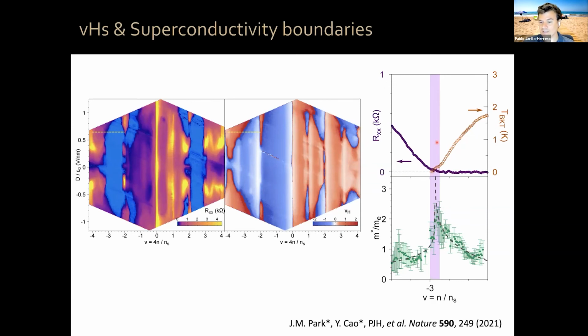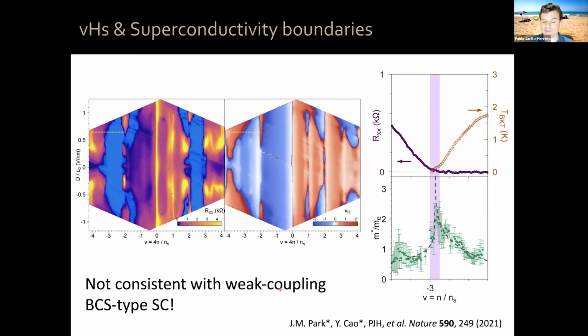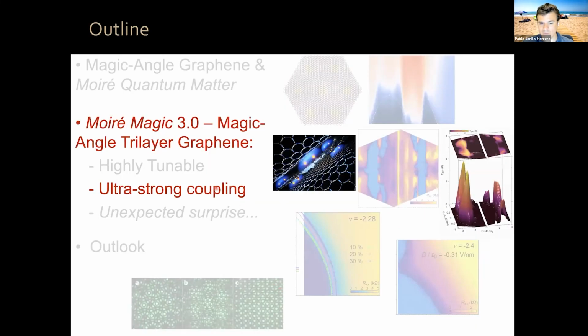And the interesting thing is that the Van Hove singularity corresponds to the boundary where TC becomes zero. And moreover, as you approach the Van Hove singularity from this side, your density of states is increasing and increasing and increasing, but your critical temperature is decreasing and decreasing and decreasing until it becomes zero at the maximum density of states, okay? So that's very much unlike weak coupling BCS type superconductivity, where your TC increases exponentially with density of states. Here it is the opposite. Not only does it not increase, it decreases with increasing density of states, yeah? So this in fact realizes ultra strong coupling superconductivity, yeah?